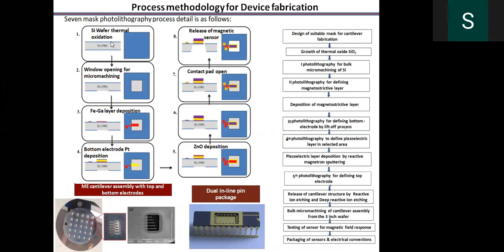First, thermal oxidation of the silicon wafer, window opening by micro machining. After that, patterning the film by photolithography technique for deposition of the iron gallium layer, deposition of the iron gallium layer. Then we have to define the bottom electrode, deposit zinc oxide, define the top electrode. We have to make the contact pad.